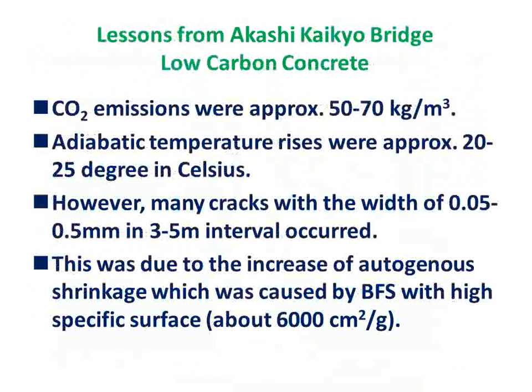And we gathered lessons from the Akashi Kaikyo Bridge low carbon concrete. One is the carbon dioxide emission was approximately 50 to 70 kilograms per cubic meter, very low. And adiabatic temperature rises were approximately 20 to 25 degrees Celsius. This was also very low. However, we got many cracks with a width of 0.05 to 0.5 millimeter at 3 to 5 meter intervals. This was due to the increase of autogenous shrinkage, which was caused by the blast furnace slag with high specific surface, 6,000 square centimeters per gram.